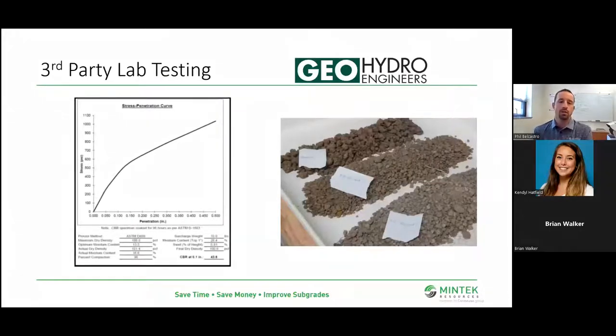So they saw some great results here after 7 days. Once again, the untreated there was about 50 PSI, and at the 7 day numbers at 4 and 6%, we got 150 and almost 200 PSI. So some good results there on the UCS numbers. And then the CBR, you can see down at the bottom of the chart there, a nice CBR there at 43, almost 44.